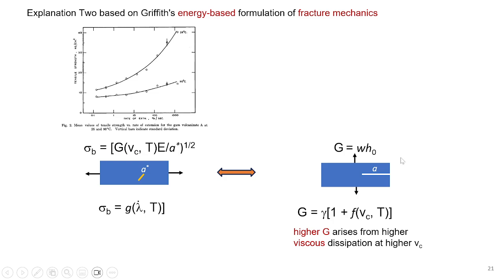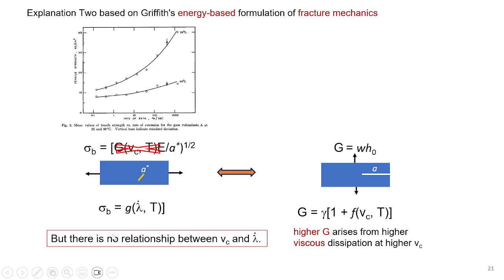So let me give you the second explanation. The second explanation was that this problem, seemingly a non-fracture mechanical problem, is a fracture mechanical problem because there's a flaw in there. So they want to explain this rate dependence through a separate experiment where you have a cut, where you learn about a relationship between the energy release rate and the rate of crack propagation. And I will not go much further except to say that this problem is really too difficult, because there's no relationship between the crack propagation of a pre-notched sample and the rate you use to stretch an unnotched sample.